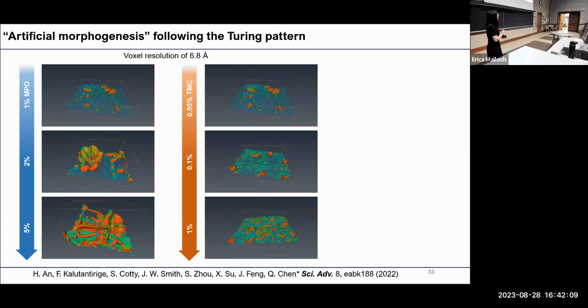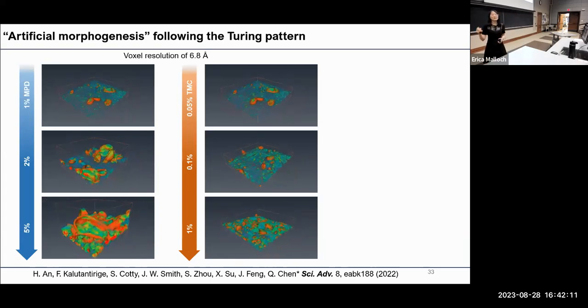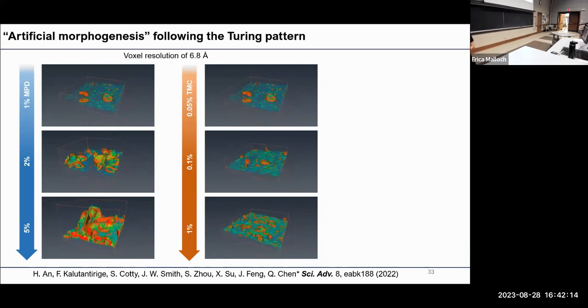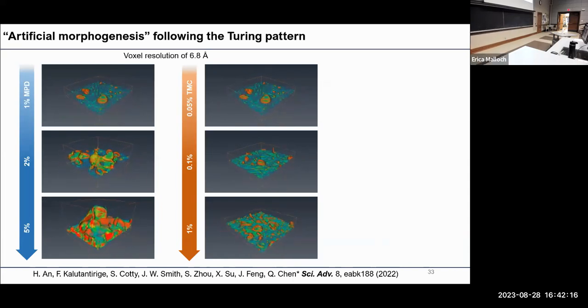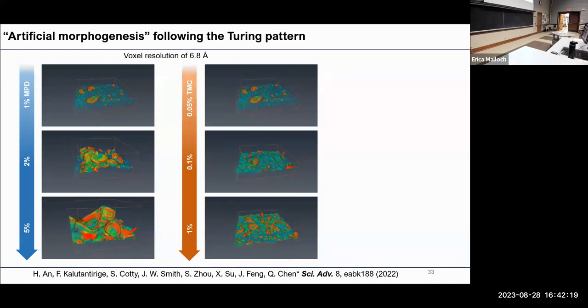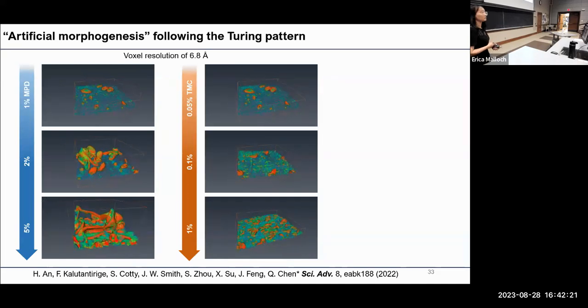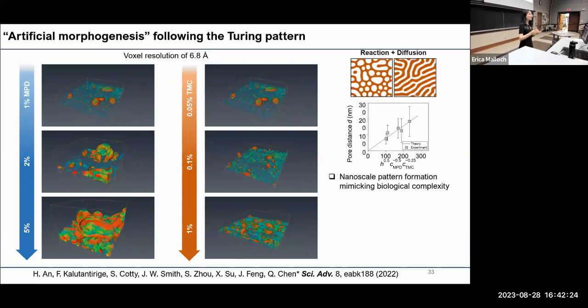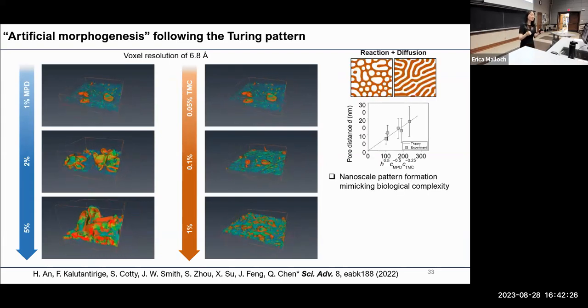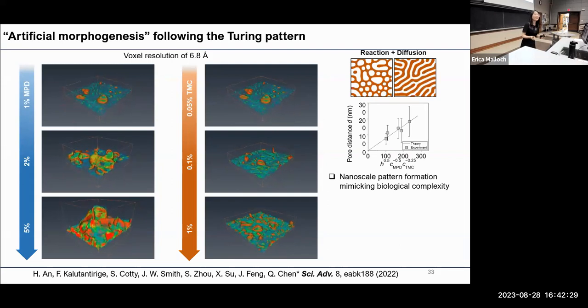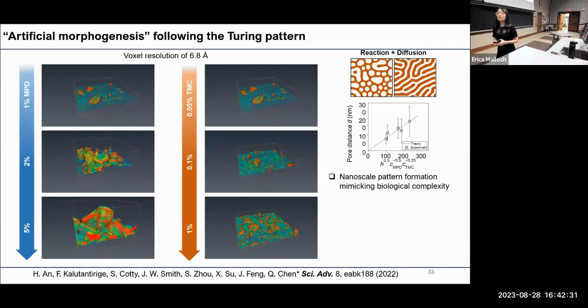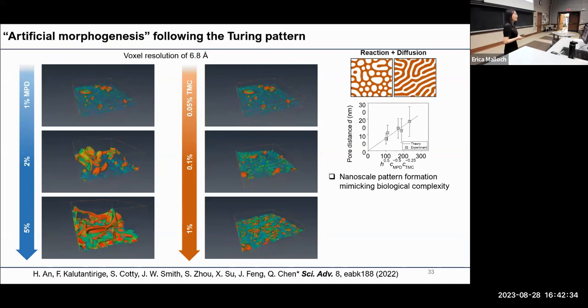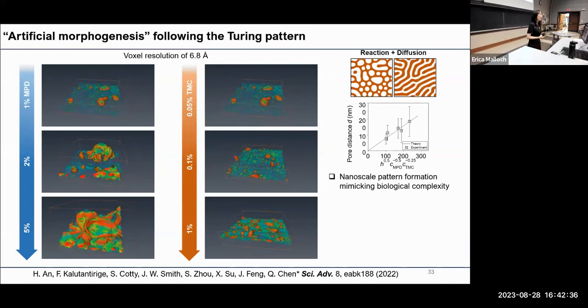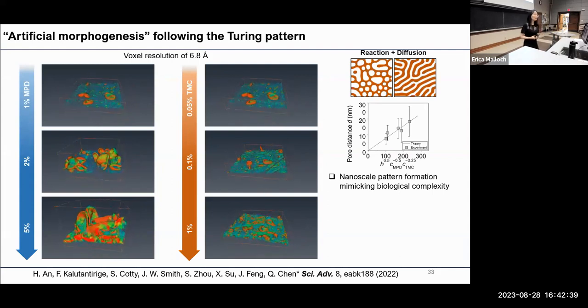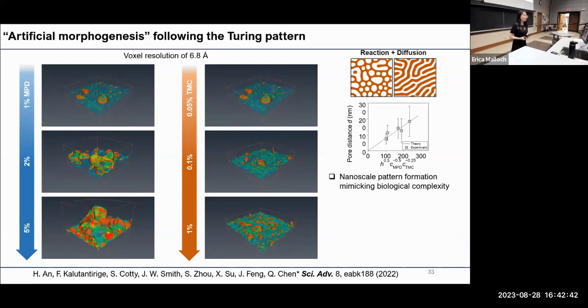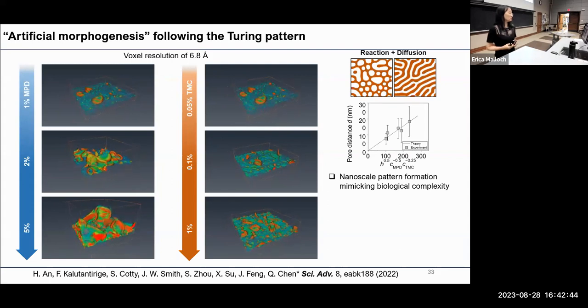The first is if you look at those samples, although they are synthesized out of the same chemical reaction with identical 2 monomers, by just changing the monomer concentration and the concentration ratio, they can have very different morphology. We later realized by measuring the inter-pore distance that this morphology development is actually controlled by a Turing pattern theory. So what this means, this is usually used to explain biological pattern formation. We here show this can also explain the artificial morphogenesis of polymeric material.